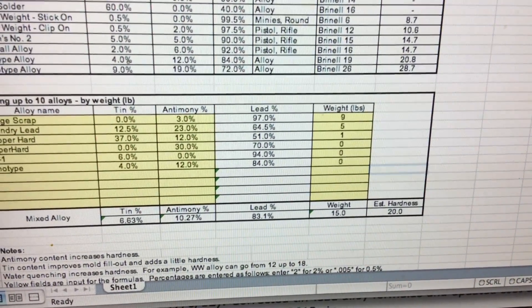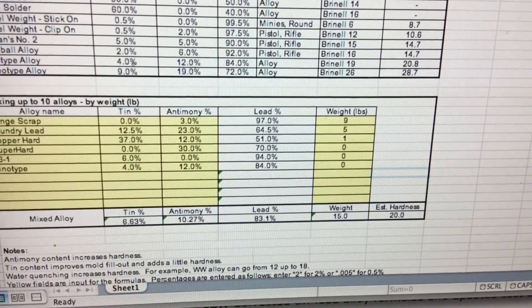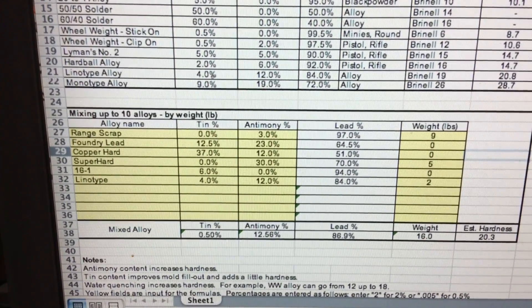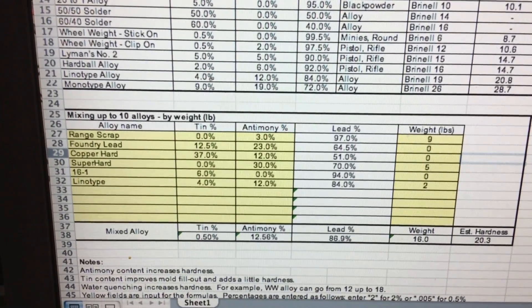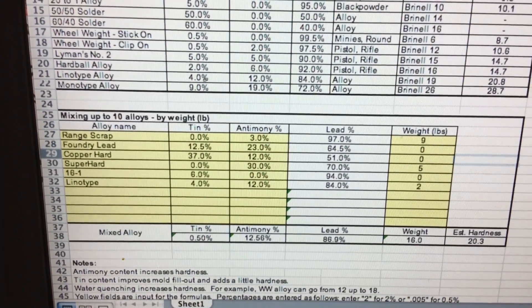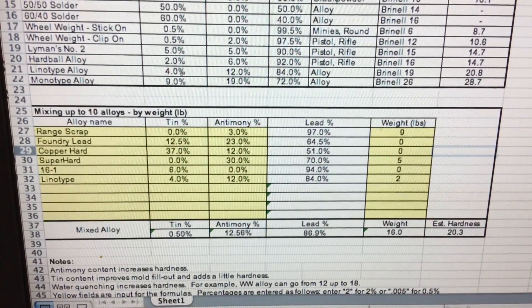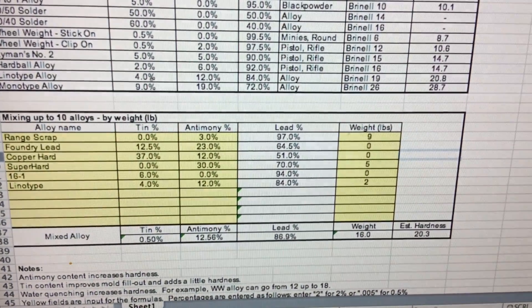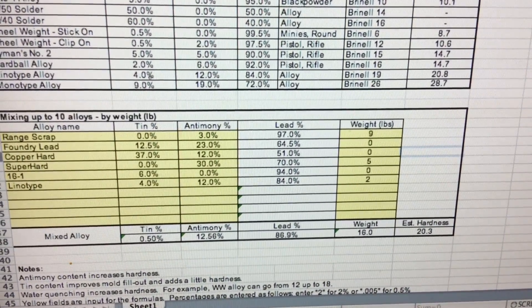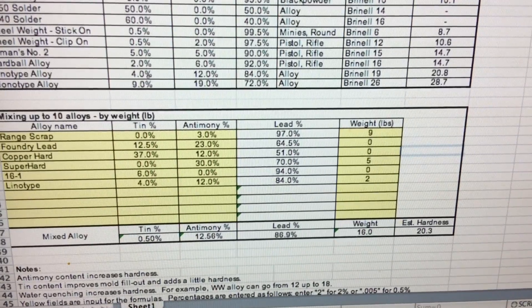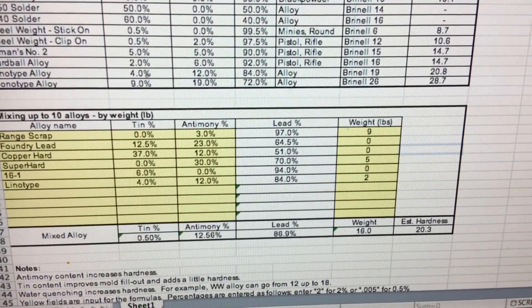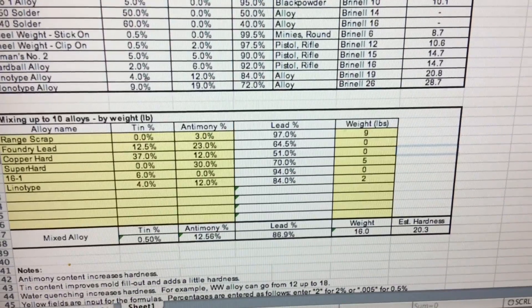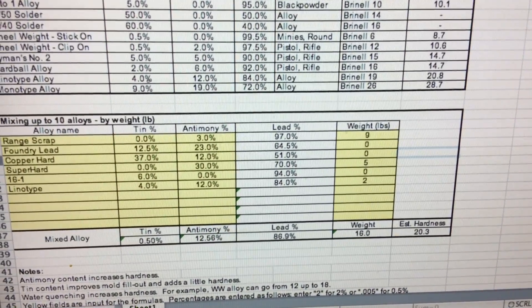If you add that up, that's 15 pounds of alloy, easy to mix in my Lee 420 pot. Or, if I've got a lot of Super Hard on hand and some Linotype, I use 9 pounds of range scrap, then I adjust my Linotype — because I want some tin in there to get good alloy flow — so I add 2 pounds of Linotype, then start playing with the Super Hard. At 3 pounds I don't get 20, at 4 pounds I don't quite get 20, but at 5 pounds of Super Hard I get 20.3 BHN. I've got a mix with tin, antimony, and range scrap that gives me 20.3 BHN, so I'll write that down as another possibility.